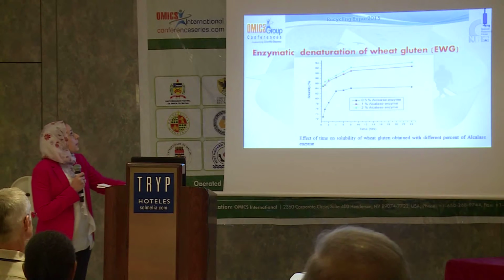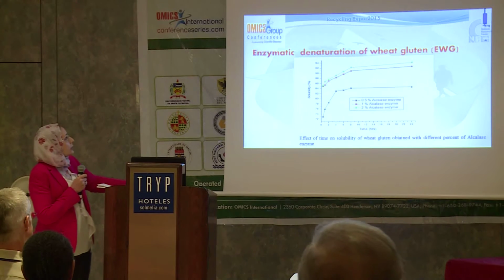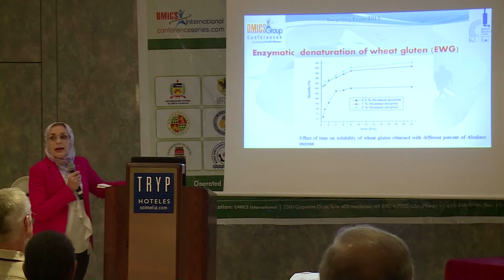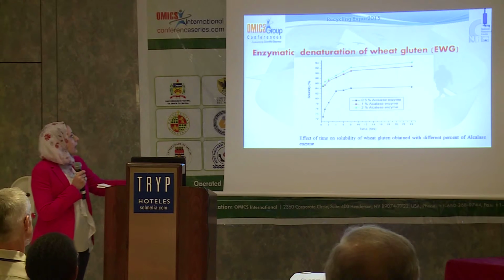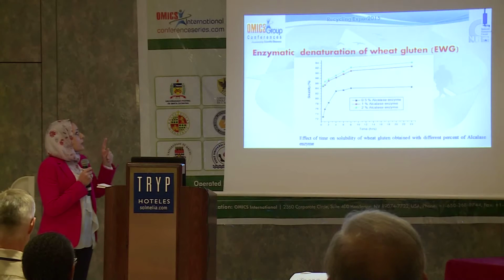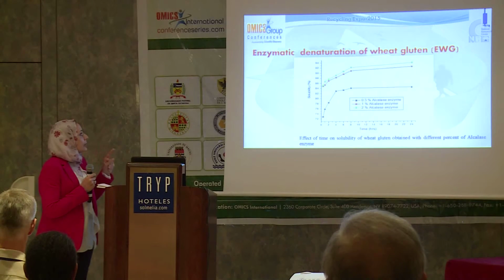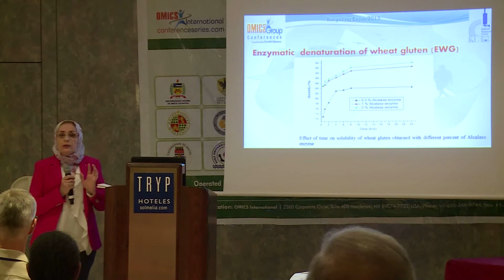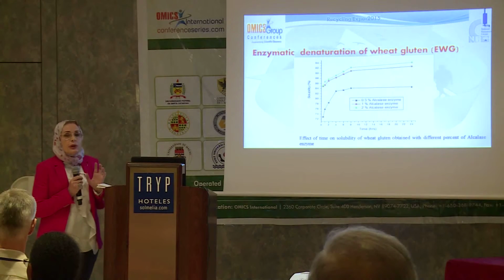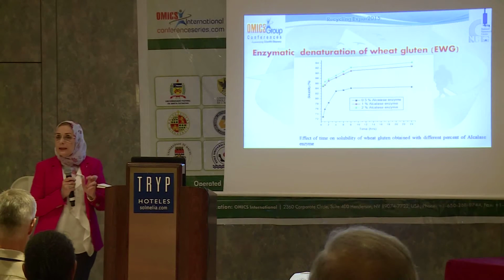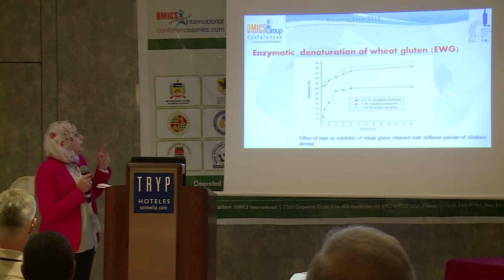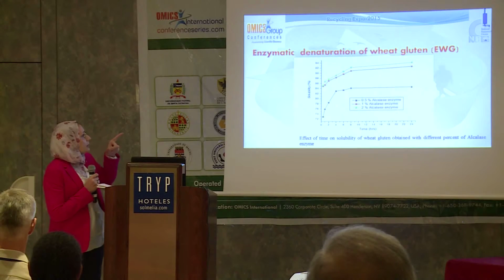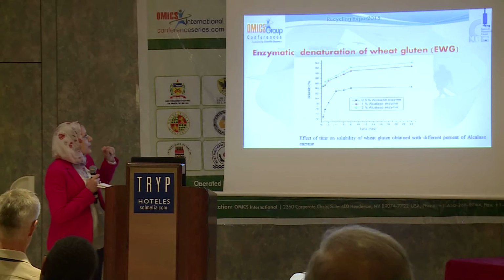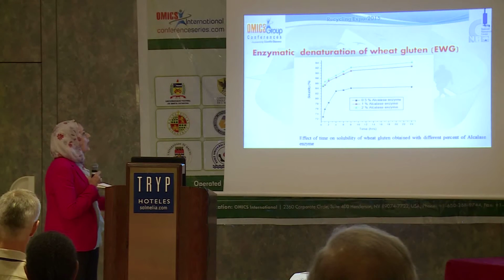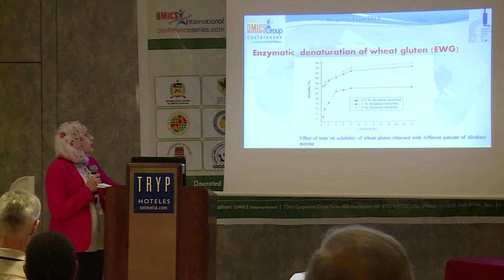Regarding the second part, which is enzymatic denaturation of wheat gluten, we used the Alcalase enzyme. The doses of the enzyme used were 0.5, 1, and 2. Our parameter here was which conditions will result in the higher solubility of the wheat gluten. We found that the higher solubility was obtained with 1% Alcalase enzyme after 8 hours.